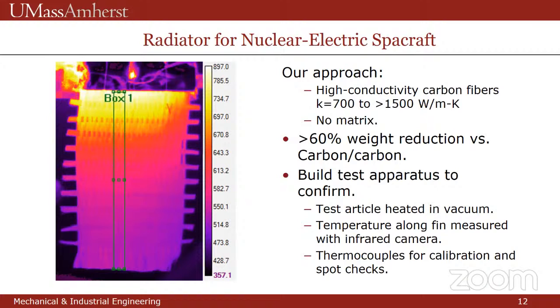If you want to think about it in fracture mechanics terms, the stress intensity goes as the square root of the crack length. And so if you have a part that's 10 centimeters wide in little bitty panels, then your crack length can be 5 centimeters. Your stress intensity is really big. If you have a 10 micron fiber, then your crack length is limited to 5 microns or so. And so your stress intensity is about 100 times smaller, so it doesn't crack. You get elastic or even plastic deformation in the braze to accommodate the thermal expansion mismatch. So the net result of all of this is that our panels are about 60% lighter than carbon-carbon, according to the model. And so we built a machine to test.